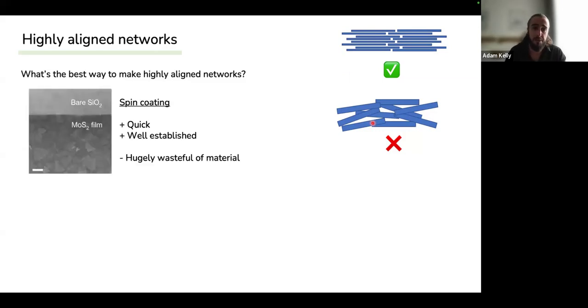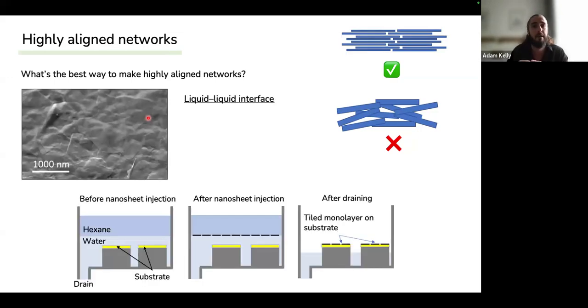Well, one way to do it is by spin coating, where the shear of the spin coating will mean you get a very, very good alignment of your sheets on top of a substrate like silicon. This is a very quick method and it's well established, but the downsides are if you only have a small amount of material, the last thing you want to do is throw it into the sides of a spin coater.